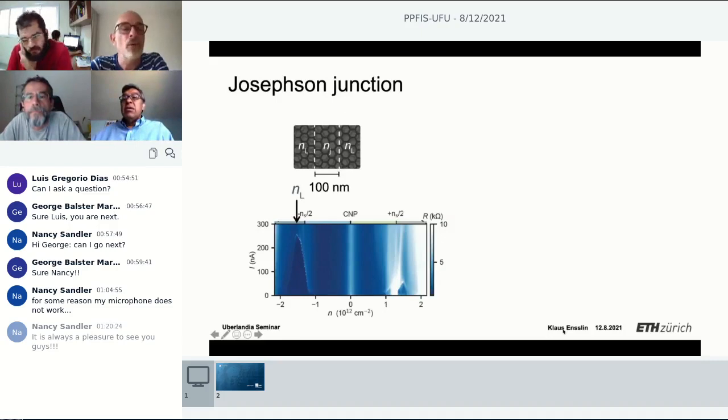Yeah, I see your point. So what we typically do is our boron nitride is typically 20 to 30 nanometers in thickness, just because you see it nicely in the optical microscope. But you could do it at 3 nanometers, and then it should be very different. Yes, I agree with that. I haven't done it. But it should make it worse, I assume, right? When the metal is close by, it probably helps screening. It will make the binding smaller. Right, it could make the binding smaller, yes.